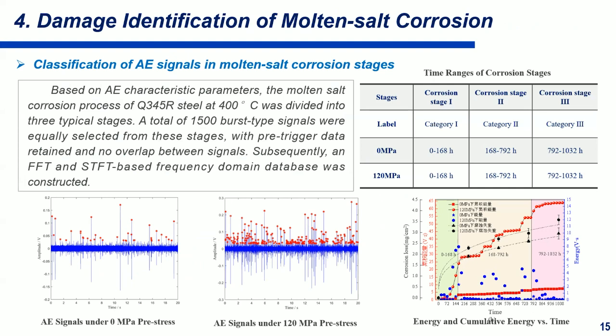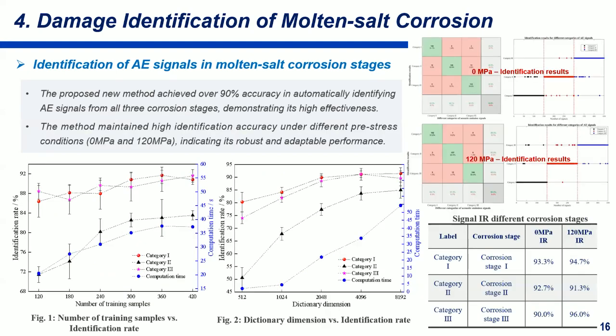So, classification of AE signals in molten salt corrosion stages based on AE characteristic parameters. The molten salt corrosion process of Q345R steel at 400 centigrade was divided into three typical stages. A total of 1,500 burst type signals were equally selected from these stages, with pre-trigger data retained and no overlap between signals. Subsequently, an FFT and STFT based frequency domain database was constructed. The proposed new method achieved over 90% accuracy in automatically identifying AE signals in all three corrosion stages.